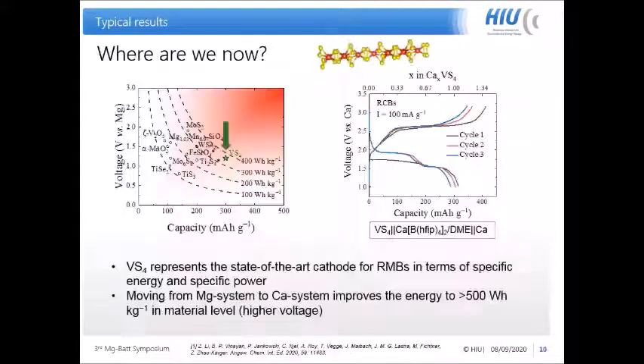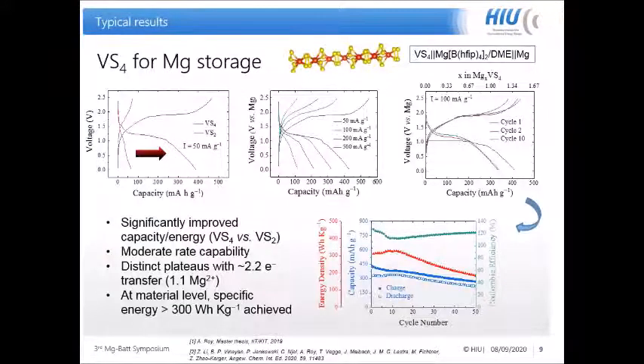But basically this 1 volt, the initial discharge, we believe is coming from the magnesium anode side. This is also the case in the magnesium-sulfur case, and in other insertion cases we have studied. We always have some activation cycle in the beginning. That's why we have some voltage drop, or voltage which is lower than the rest of the cycles. So I think it's mostly contributed from the magnesium side.